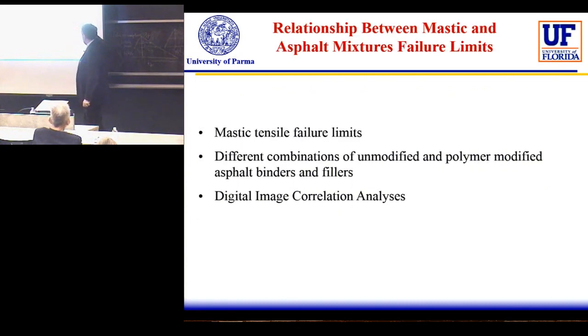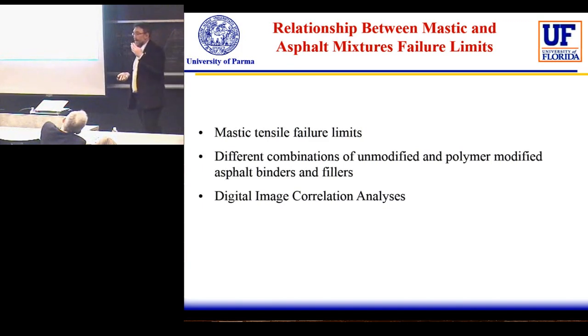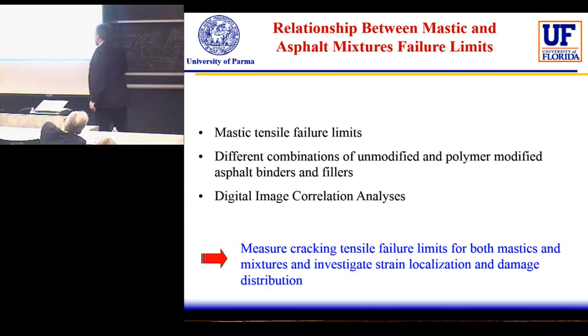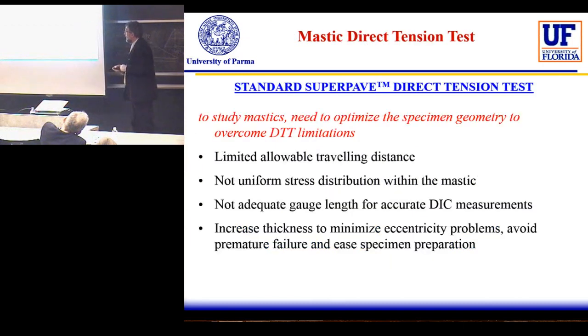So, what we were looking for was to define the mastic tensile failure limit with different combinations of unmodified and polymer modified bitumen and different fillers. And again, we used digital image correlation to have a more precise evaluation of the strain field in the material. And we applied this, we worked on both sides, tensile failure limit in mastics and tensile failure limit in the mixture. To do that, we decided to move to a very simple test configuration in order to have a very simple characterization of the stress field.